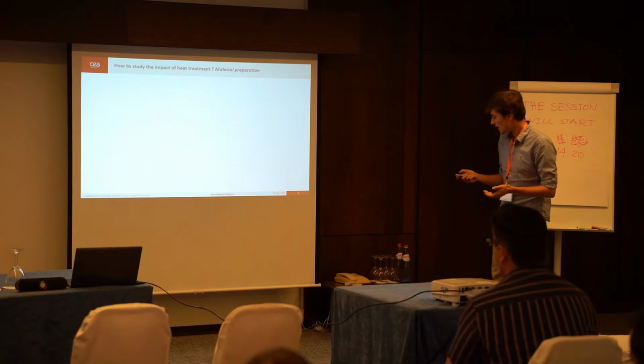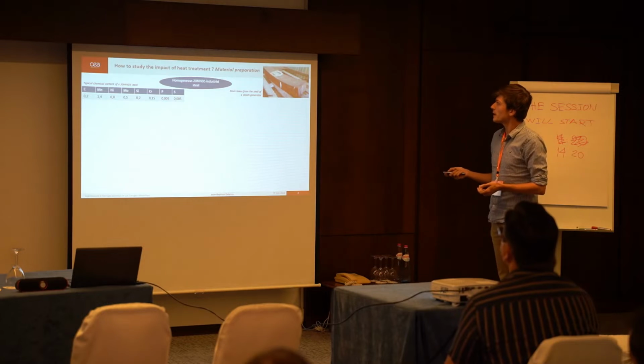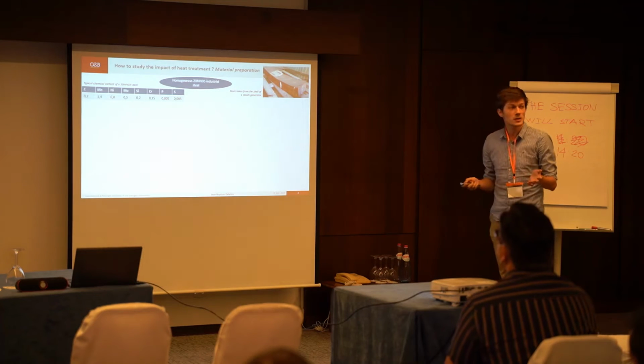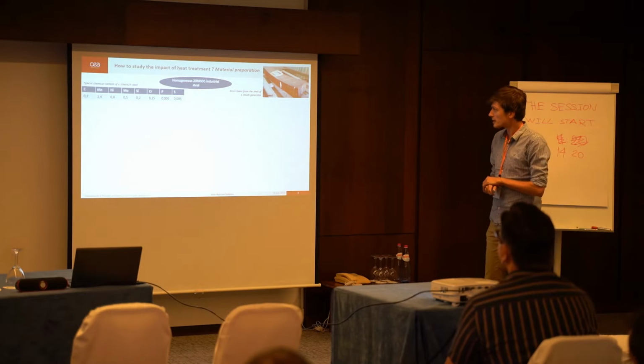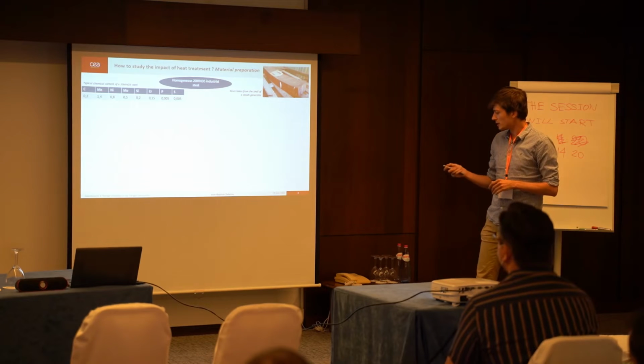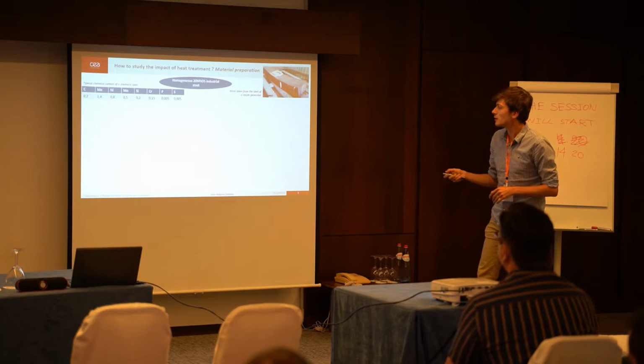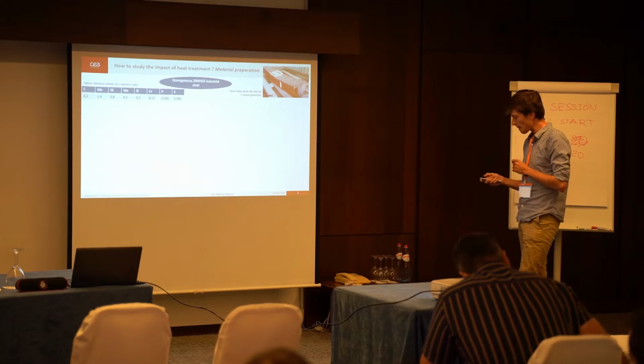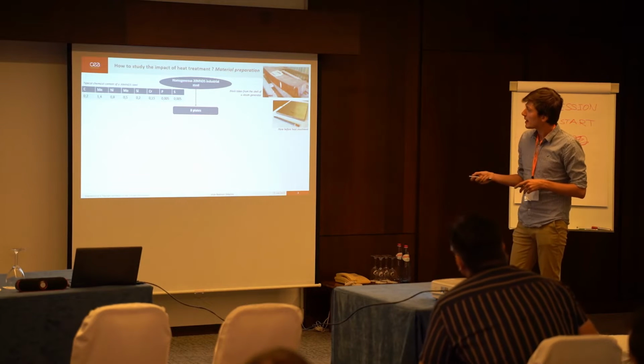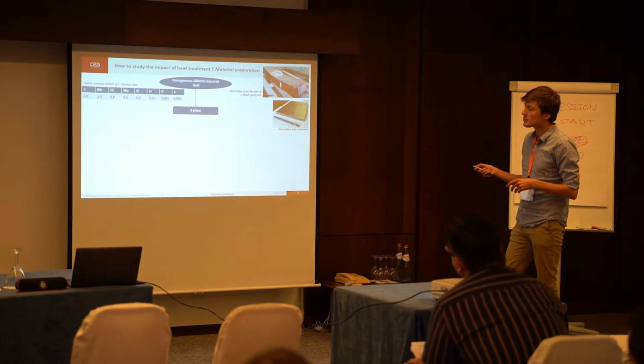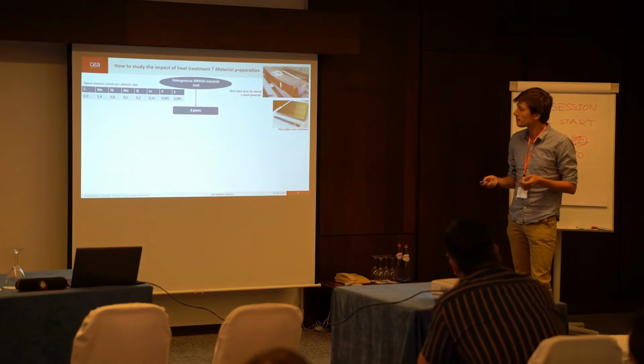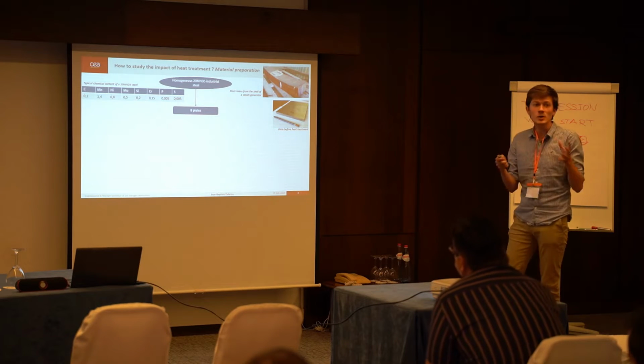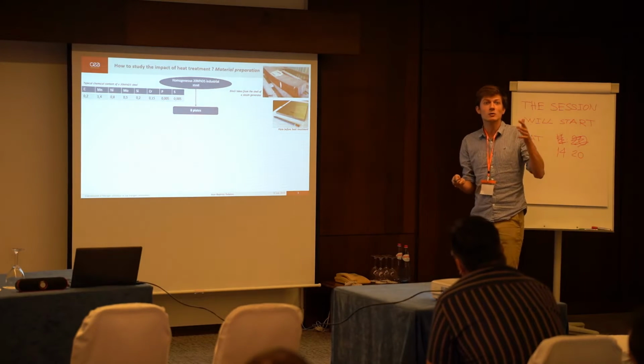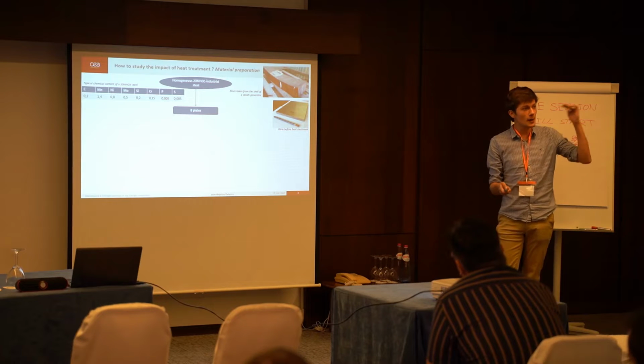So, what is our methodology to study the impact of heat treatment conditions? We start with a homogeneous industrial low alloy steel used in nuclear power plants. You have the typical chemical contents of such steels in the table here. And then we cut 8 plates from the block that you have here that comes from a real part. And we are going to heat treat those 8 plates so as to replicate the heat treatment that happens at